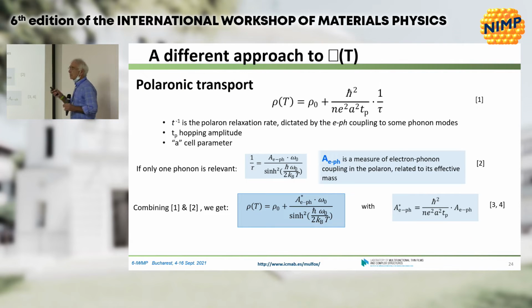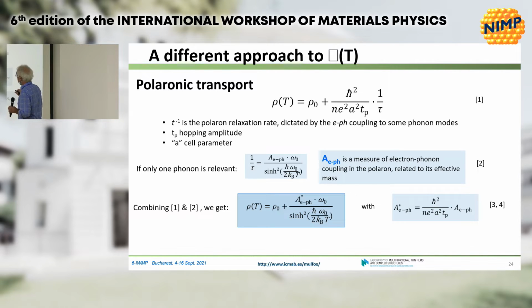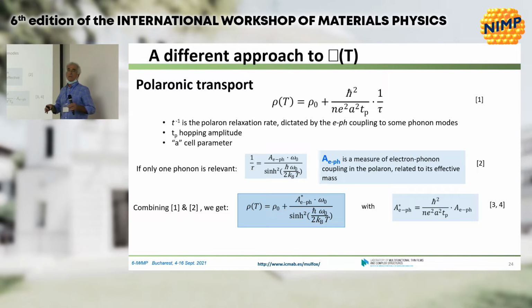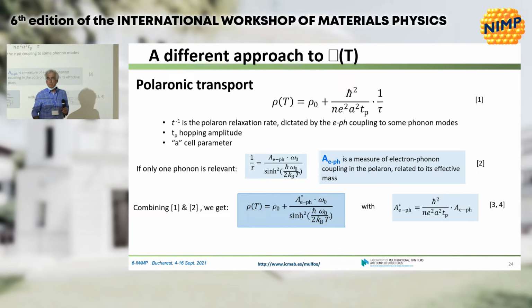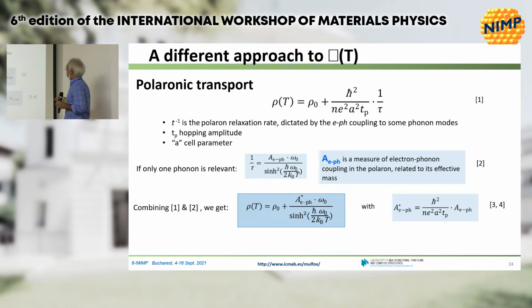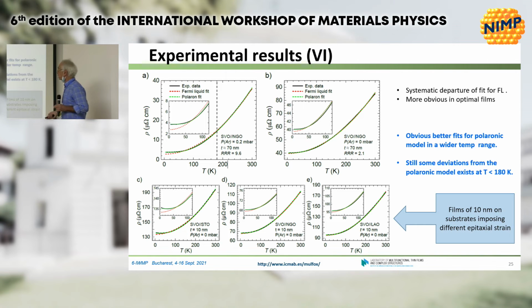And here is the resistivity described in the simplest possible way in a polaronic system, in which the electron-phonon coupling is related to this term, 1/tau, described here, in which I'm taking the simplest approximation in which the carriers are only coupled to one particular phonon, omega 0, whatever it is. And now let's see if this data can be described in that way. It's very easy. Now you can fit the data using this expression, and we can extract this parameter and omega 0 from the fit. And that is what you get.